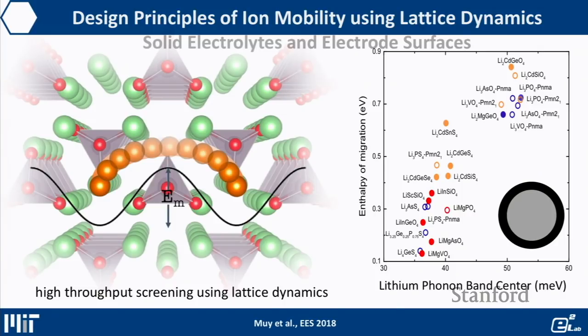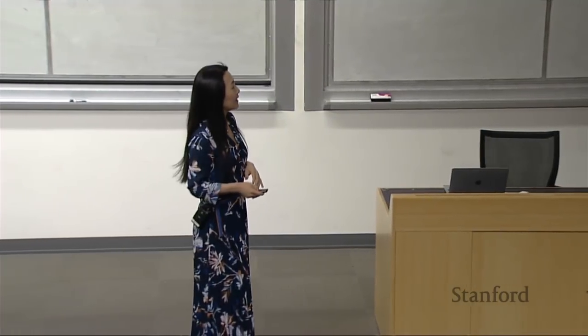So if you want to have a stable structure that only conducts lithium, without the other ions moving, we would like to have the other inactive or non-mobile cations have a very high phonon band center, right? So this is essentially the key design principle. You want to have softer phonons for the mobile species, but harder phonons for the structural ions. So we're currently utilizing this design principle to see if we can generate a large database for the phonons through which we can actually do discovery and design of new electrolytes.